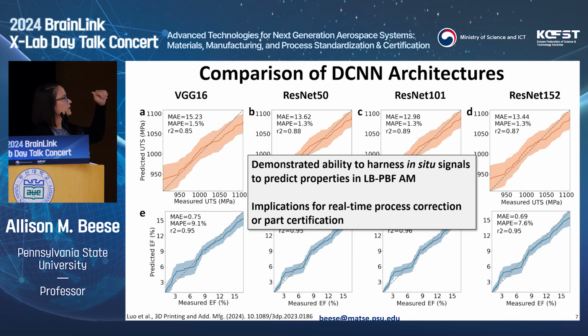So the idea here is that the first thing that we can do is we have demonstrated the ability to harness these in situ signals to predict properties. So strength and ductility are shown here, and we've done this for different alloys. The second thing that this shows us is that this has implications for real-time process correction or part certification. So you could be processing a part and collecting these data to understand that in a particular region you have lower strength or ductility than you need for that application, meaning that you need some sort of intervention.